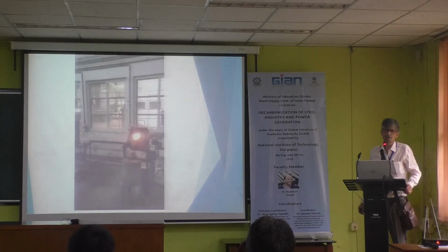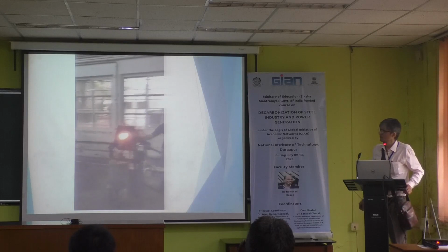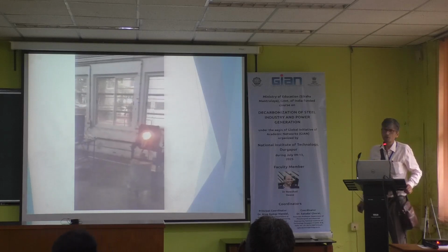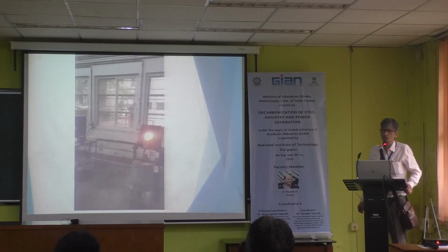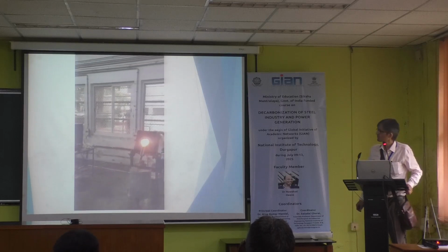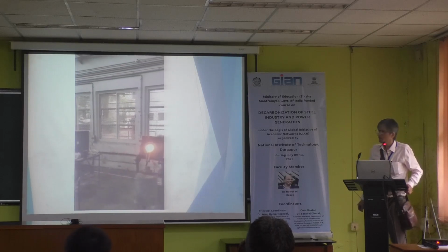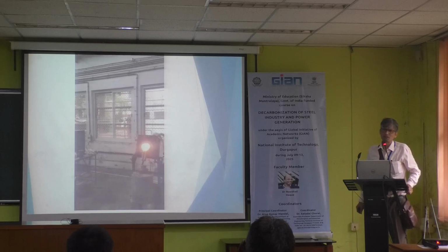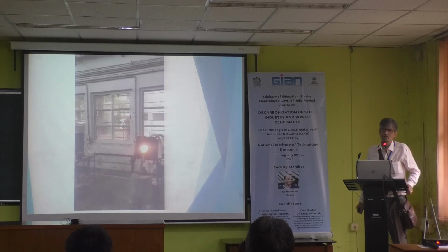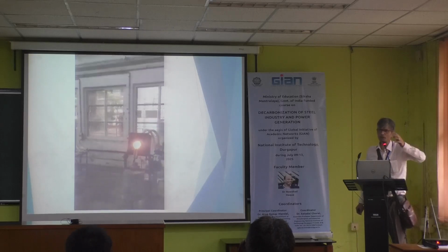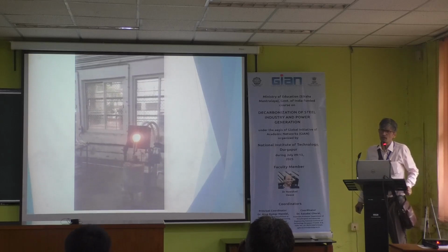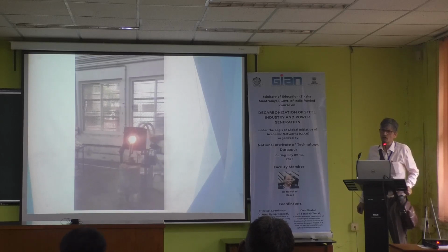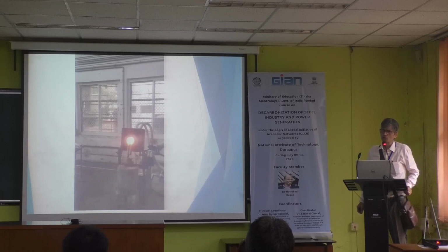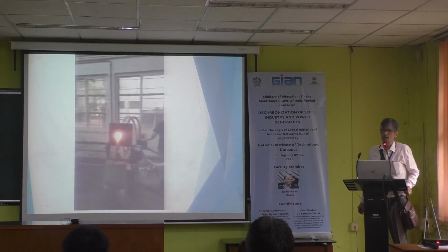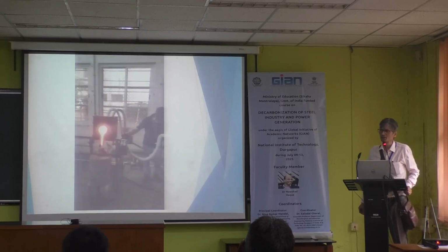We did 1 or 2 trials to see what the effect on the phosphorus of the hot metal or DRI would be. We have used a synthetic slag, a combination of limestone, silica and iron ore together to make a slag of CaO, FeO, SiO2 kind of system.